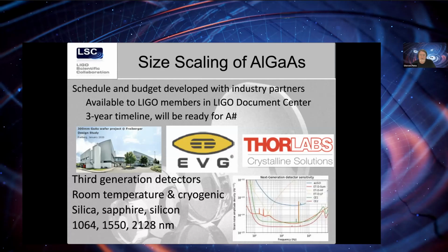Freiberger Technologies grows the original GaAs wafers that are grown in a very large boule that takes a few years, cut, polished, waferized, and then they are passed on to EVG, which is the MBE facility, the molecular beam epitaxy facility, where we will actually grow the coatings. And this is all administered by Thorlabs Crystalline Solutions, which is led by Garrett Cole, who originally developed these coatings. And that process from the original boule growth through to the development of the coatings will take about 3 years.